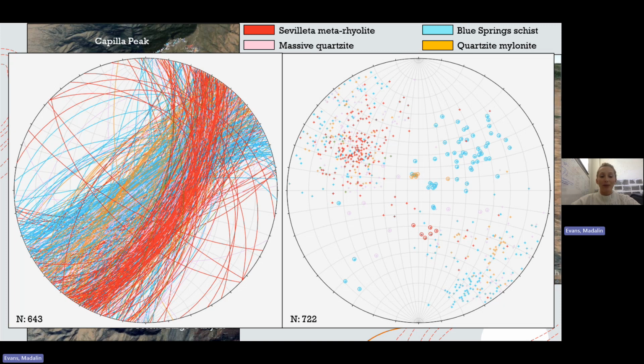So if we look at this in more of a map view at a smaller scale, Monte Largo Canyon is here from this circle, and Trigo Canyon and Capilla Peak are from this circle here. The Sevilleta metarhyolite, which is in red, has been dated to be around 1662 million years. The massive quartzite in pink has a northwest depositional contact with the Blue Springs schist, and it has a mean thickness between 250 to 600 feet and occasionally reaches up to 2,600 feet. The Blue Springs schist, which is in blue, is dated to be around 1601 million years. The quartzite mylonite, which is in orange, also has a northwest depositional contact with the massive quartzite and has an average thickness between 15 to 30 meters.